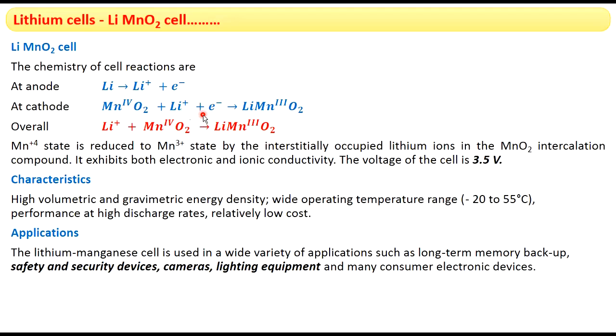Now both Li+ and one electron will reach the cathode, where they will meet the MnO2, and Mn(IV)O2 plus Li+ plus electron gives rise to LiMn(III)O2. LiMn(III)O2 is formed. So the overall reaction will be Li plus Mn(IV)O2 gives rise to LiMn(III)O2. So this is a primary battery, and here manganese from +4 oxidation state is reduced to +3 oxidation state by the interstitially occupied lithium ions in the MnO2 intercalation. Okay, in the MnO2 layers, these Li+ ions are there. Those Li+ ions will reduce the Mn(IV) to Mn(III), and this LiMnO2 cell will produce a maximum of 3.5 volts. And the MnO2 intercalation compound will exhibit both electronic and ionic conductivity.